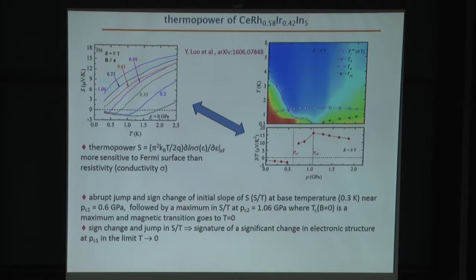So the resistivity really isn't so sensitive to details of the Fermi surface or electronic structure at the Fermi surface, but thermopower is. And in this case, we show a summary of the thermopower measurements as a function of temperature for various fixed pressures. And what we see is that at low pressures, the thermopower approaches the origin with a negative slope, but at higher pressures, the thermopower approaches the origin with a positive slope. And these initial slopes are summarized in this plot here at various different pressures.